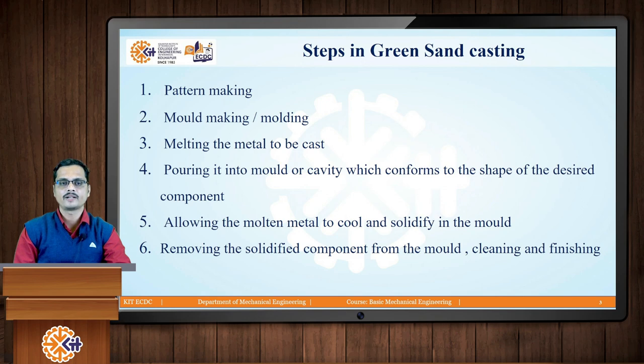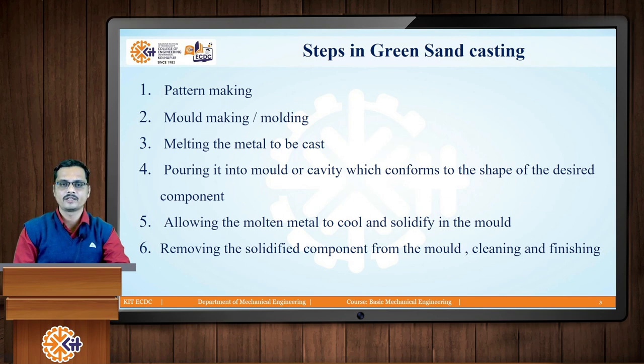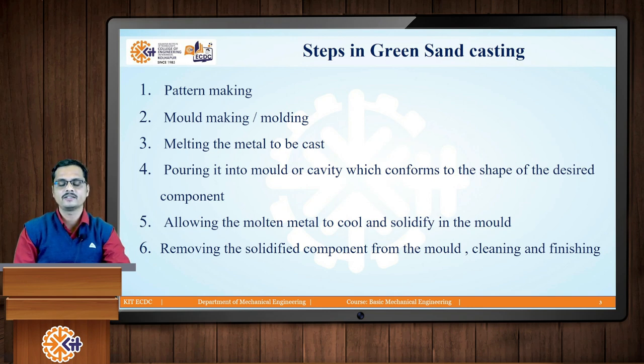Dimensions of a pattern are always slightly more than the dimensions of the casting to be obtained. After preparing the pattern, we put it into a sand mold. The sand mold is prepared with molding sand which consists mainly of silica sand with 4 to 5 percent moisture and binders. By using this pattern we are creating cavities inside the molding sand, and that second process is called mold making or molding.